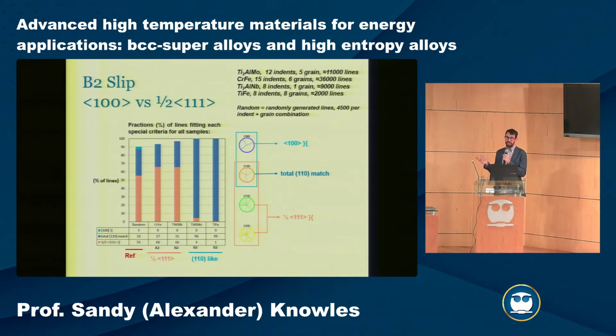So we've applied this to different intermetallics. We really want intermetallics that are going to slip on <111>. When we look at an iron chromium alloy, this has a characteristic slip of <111>. We see a great prevalence of 110 type planes, as well as 112 and 123 planes. This combination of planes together gives a characteristic slip of <111>. Whereas if we look at our titanium iron system, this one mostly has slip from 100, with an occasional 110 as well, which indicates that we're getting a Burgers vector of <100>. So we don't have the deformation mode that we really want in the material.